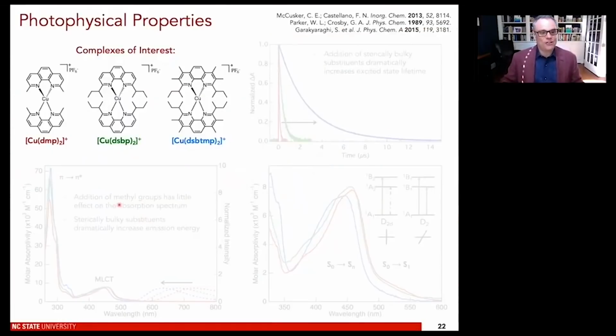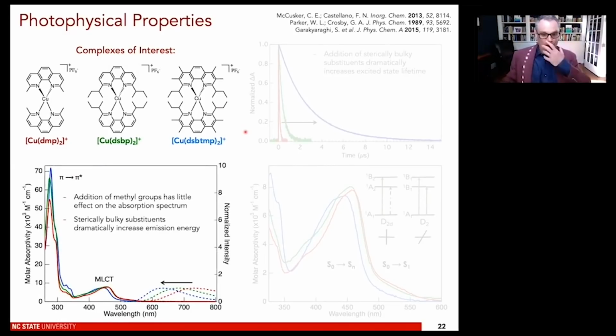So here's a typical series of three compounds. And what I want to illustrate to you is that this was our new design, and it was based conceptually on the idea that MacMillan originally had. If you put 3,8-methyl groups next to the 2,9 substituents, it forces the 2,9 substituents in a particular direction towards the coordination site. They can't bend outward. And that's a very important design criterion, because this molecule distorts the most, it has the biggest Stokes shift. This molecule distorts a little less, it has less of the Stokes shift. This one is really sterically arrested, it has the least Stokes shift.